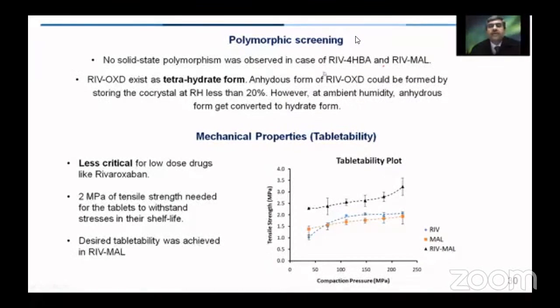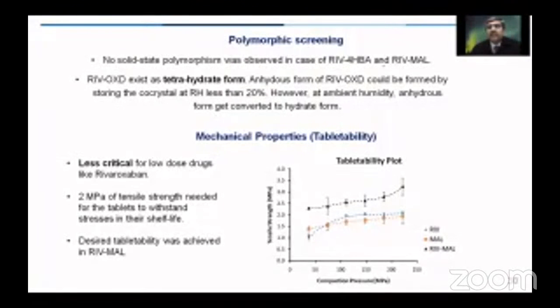There were no polymorphic forms obtained for the co-crystal with 4HBA and with malonic acid. The co-crystal with oxalic acid exists as a tetrahydrate form. Anhydrous form of oxalic acid co-crystal could be formed by storing the co-crystal at a RH value less than 20%, which was very obvious and could be seen in the DVS studies that we discussed earlier. However, at the ambient humidity, the anhydrous form gets converted into the hydrate form.